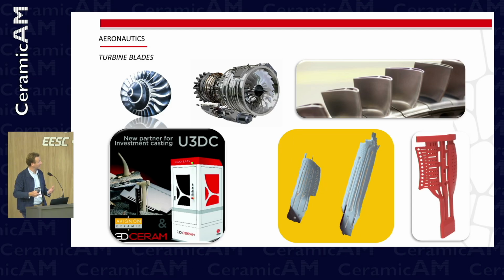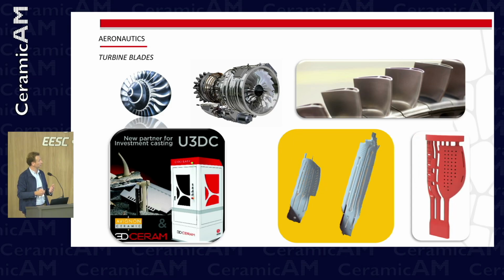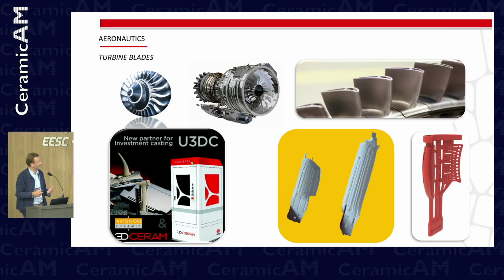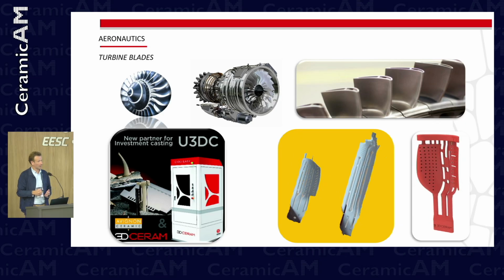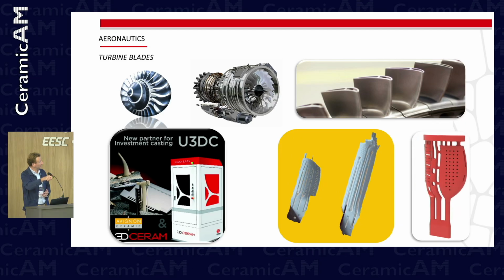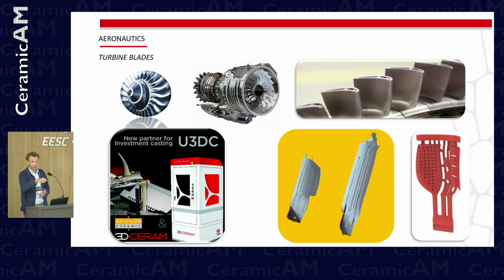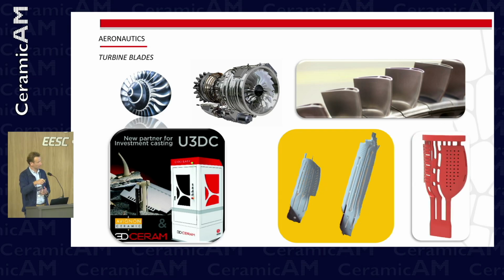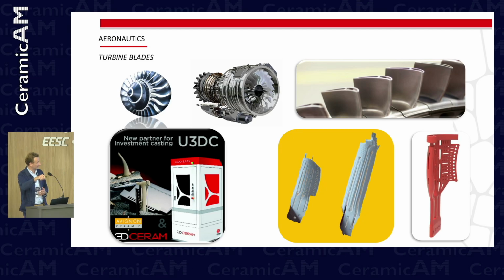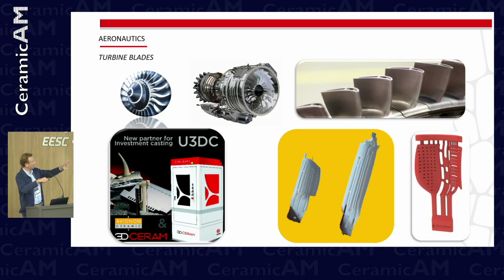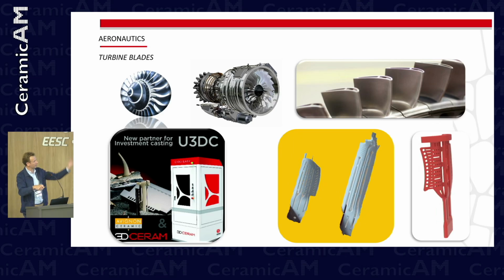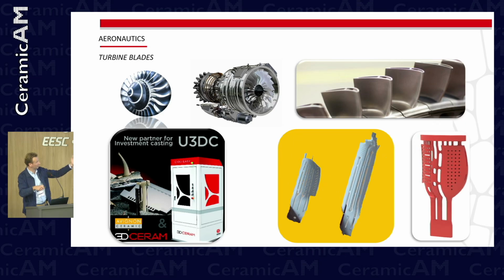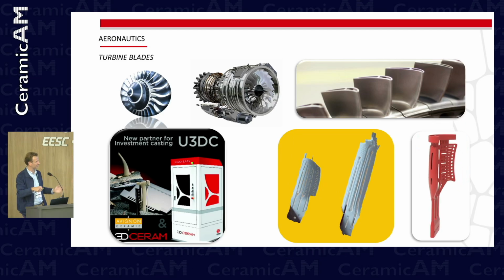Another possibility, I'm not sure you know this technology, but it's investment casting for precision foundries. When they want to produce this kind of part for aircraft engines in metal, you need a ceramic core inside this part as a mold, as a negative mold. So it means that it's silica-based material. They are going to cast the metal around and after dissolve the ceramic core inside. And for this part, you need porosity. So it's a very specific application.